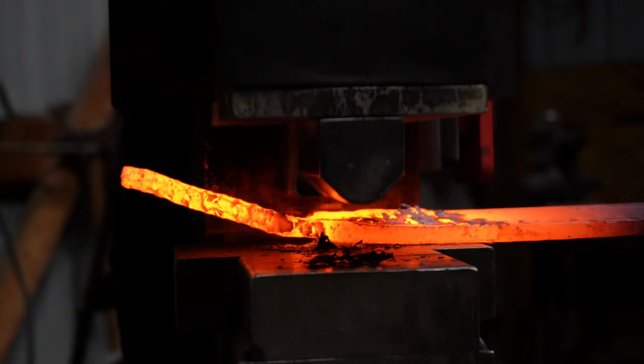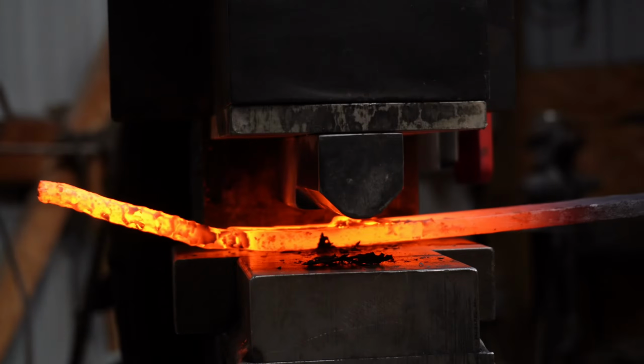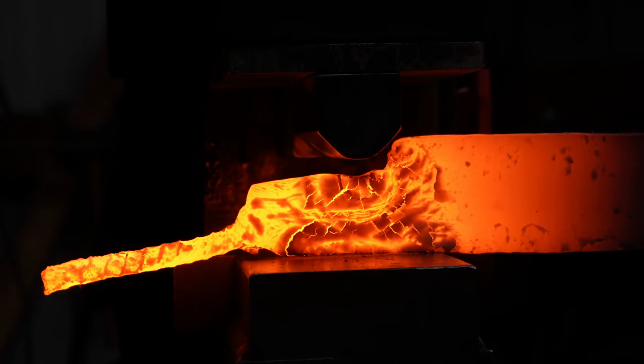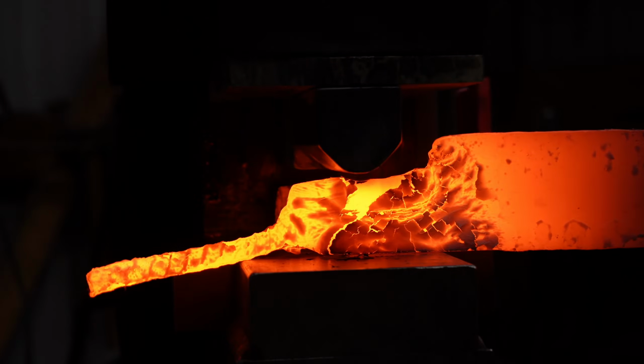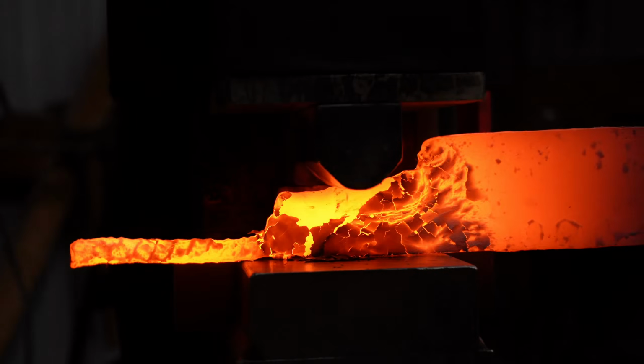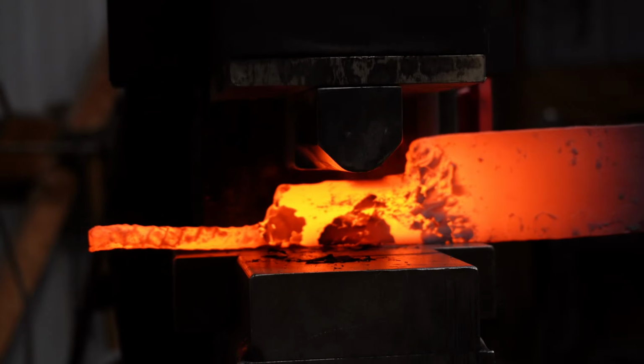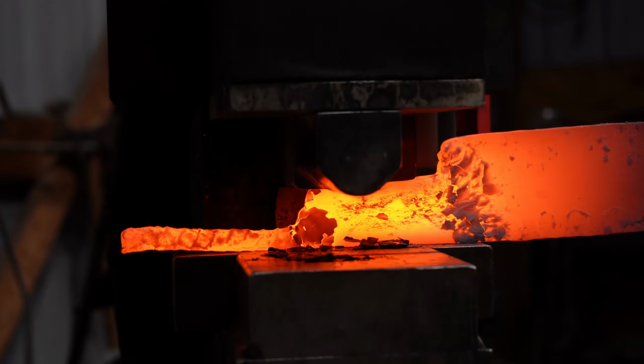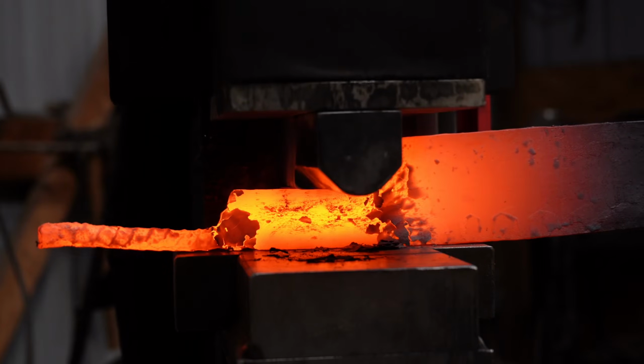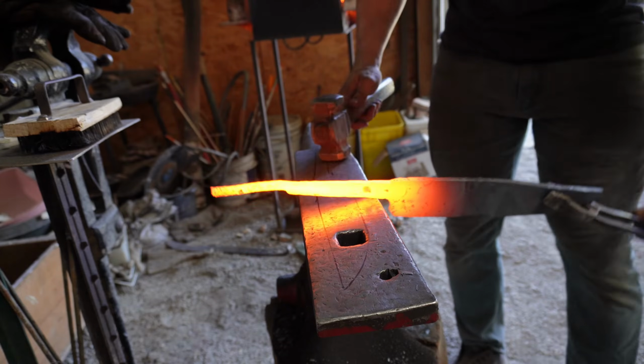If I can do this with nothing opening up and no seams popping, that means I have really strong forge welds all the way around. Throughout the entire process of drawing out this blade and the tang, not a single seam opened up, which I'm very pleased with, because the failure rate on projects like this can be pretty high if you're not careful.